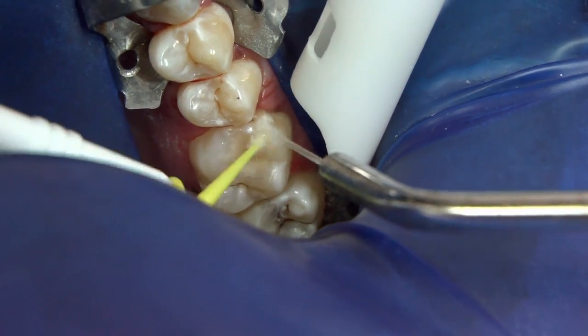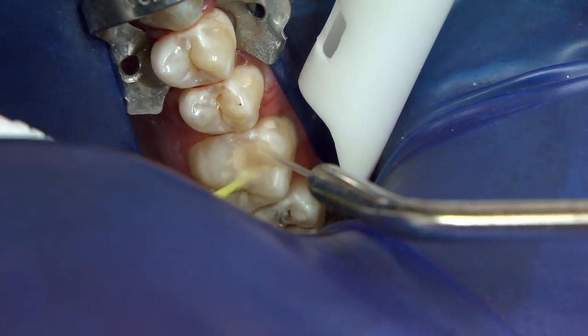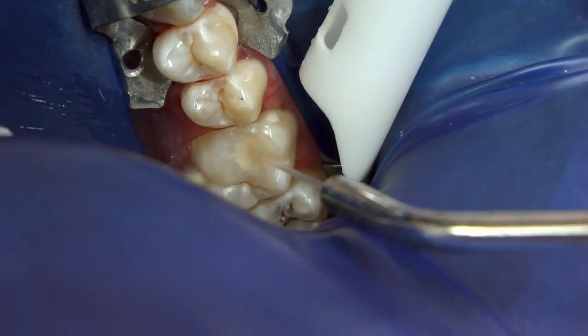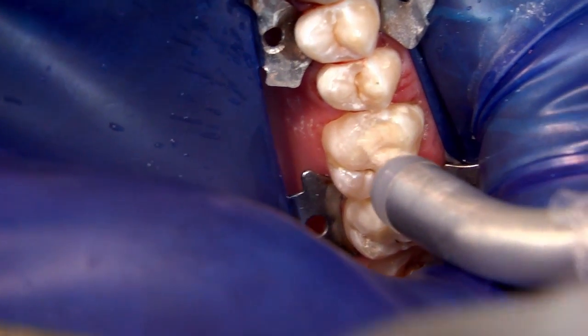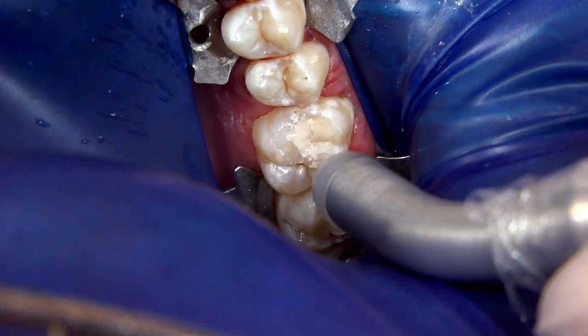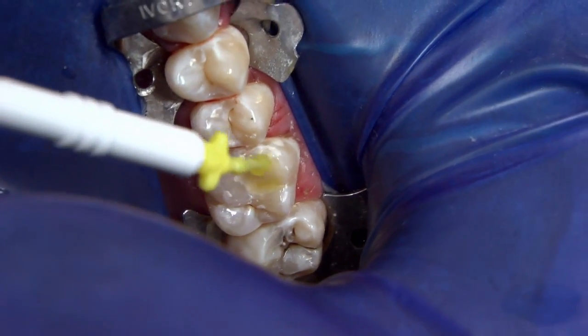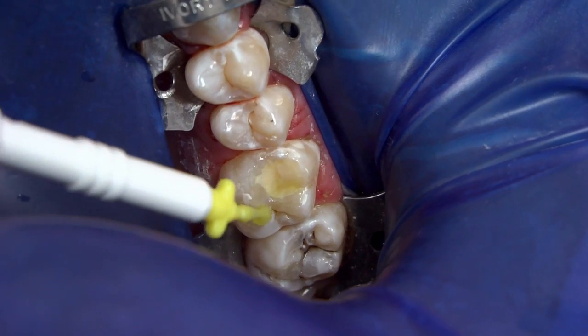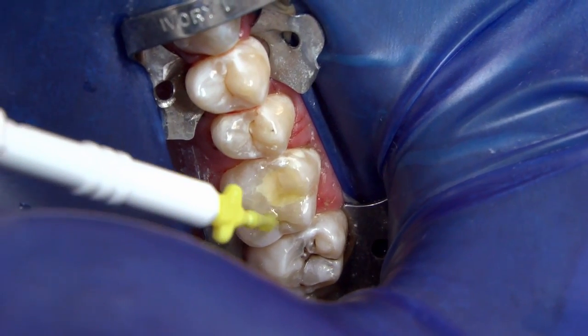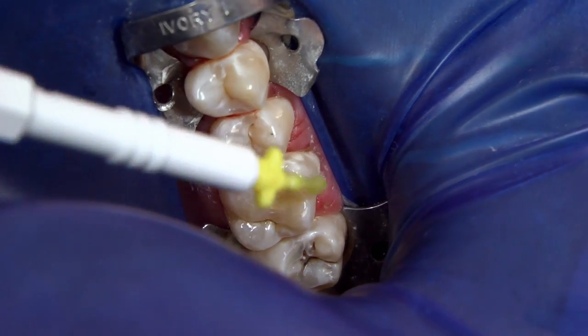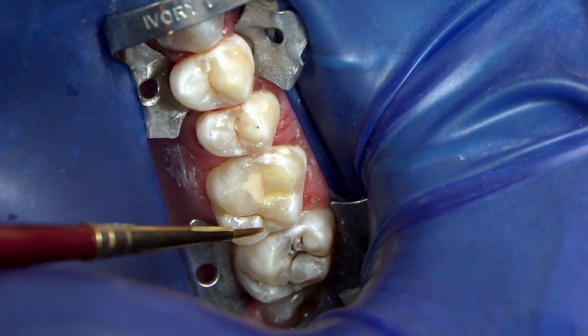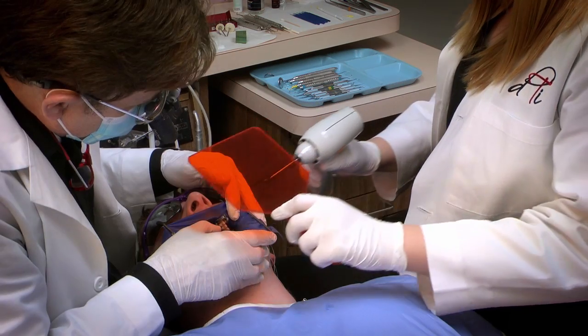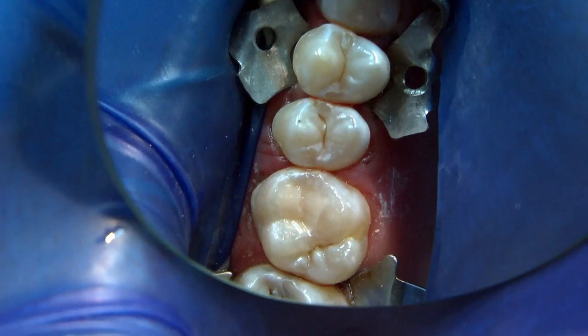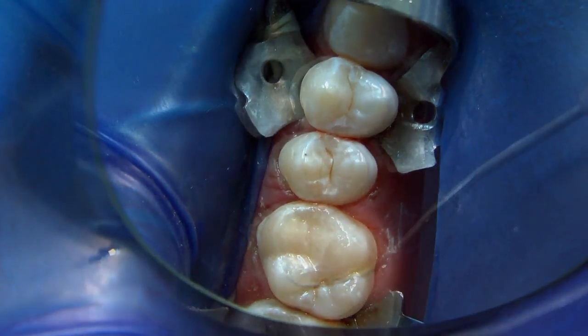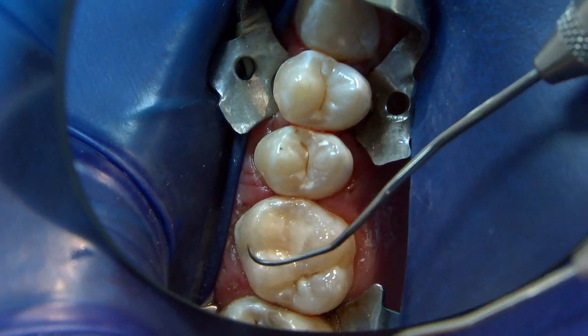After finishing, rinse with water and scrub with an applicator brush to remove any surface particles or contaminants and thoroughly air dry with a warm air tooth dryer by A-dec. A thin layer of self-adhesive G-Coat Plus by GC America is applied to all exposed glass ionomer surfaces and to adjacent tooth surfaces including the distolingual fissure with a sable brush or a micro-tip applicator and light cured for 20 seconds. The completed restoration. Notice the harmonious integration of this improved glass ionomer system with tooth structure.